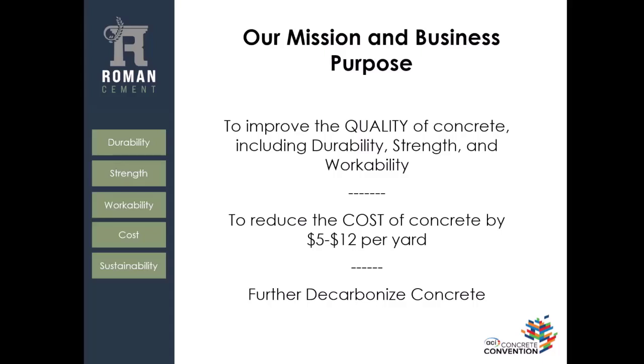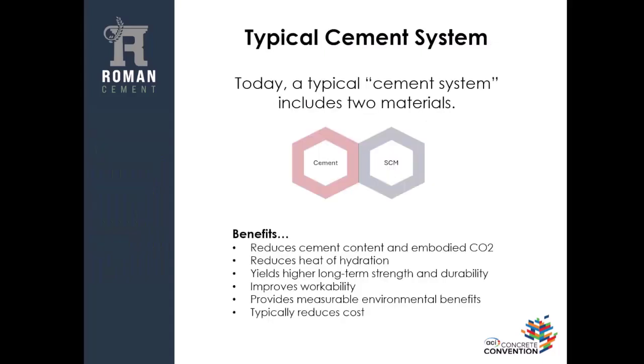Anyway, we were able to redesign several mixes of ready-mix companies in California and in Utah, and we were able to, from the materials cost standpoint, reduce the cost by $5 to $12 per yard. We were able to improve the quality of concrete. We don't try to increase the strength, we try to match the strength, but we did some durability tests, and they came out very good, and the workability is very good. Even though we call ours a low-carbon concrete, because of the way in which we use a mineral filler, we're able to maintain very good workability.